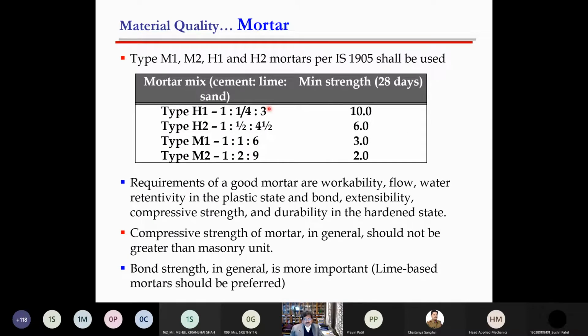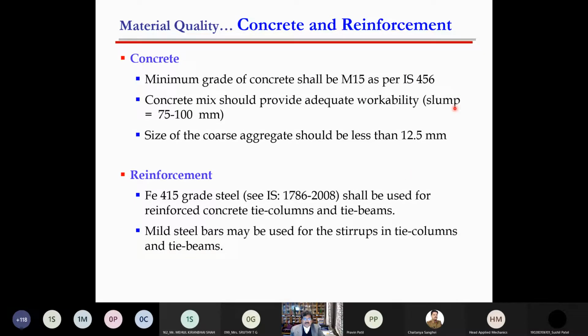About the mortar, it's better to use cement, lime, sand mortar. This is not very expensive. Medium mortar M1 is 1 part cement, 1 part lime, and 6 parts sand. It gives you a strength of about 3 MPa. What you need is good workability, and adding the lime does that. Somehow the use of cement sand mortar is not good, and this is kind of a deviant behavior propagated by our building codes. Concrete should be at least M15 for your tie columns and tie beams, and for reinforcement you can have Fe415 minimum, but you can use a higher grade if it's not available. Mild steel can be used for the stirrups.